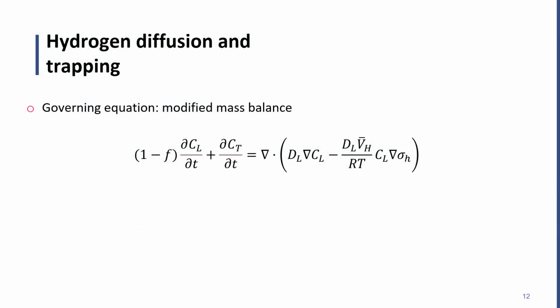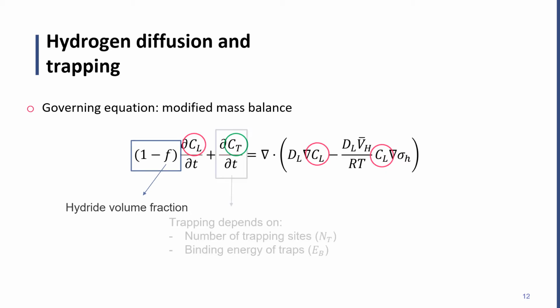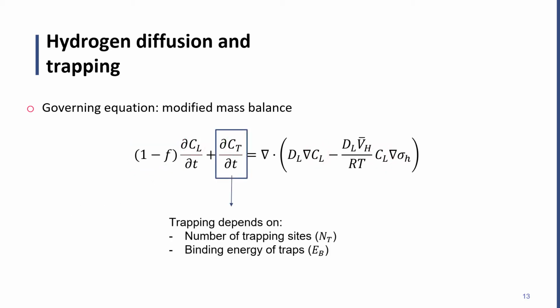This is the equation governing diffusion, and here we can distinguish between hydrogen in lattice sites and trapped hydrogen, or hydrogen in trapping sites. The magnitude F represents the hydride volume fraction, and 1 minus F is added to include the rate of interstitial hydrogen which is forming hydrides. The trapping term can be regarded as a sink term, and it depends on the number of trapping sites, but also on the binding energy of those traps.